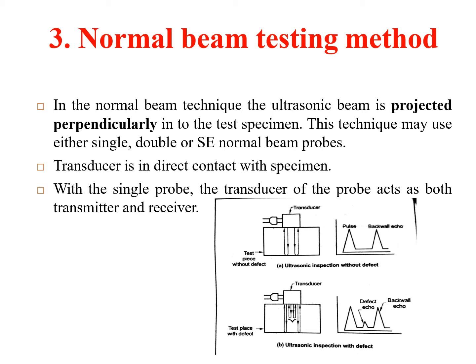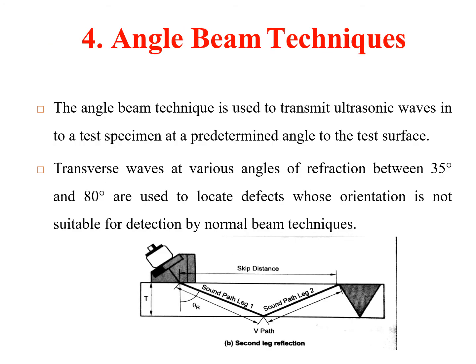Now, one of the issues with this is that not all defects are parallel to the surface. There can be inclined defects. There are defects which are inclined to the surface. Using this normal beam testing method, it is difficult to completely analyze defects that are inclined to the surface. So this is one of the main disadvantages. Here, the transducer of the probe is acting as the transmitter as well as the receiver. So both transmitter and receiver are placed inside the transducer itself.